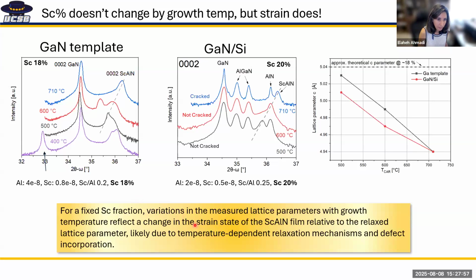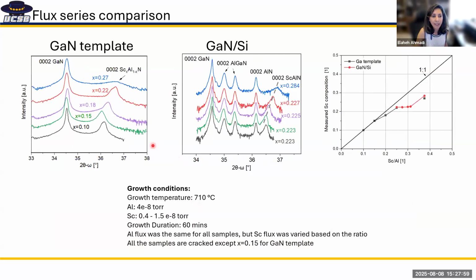incorporation. Another thing we have looked at is the fluxes basically, and what we have seen is that as we increase the scandium to aluminum ratio for smaller compositions, it changes linearly, but as we go to higher scandium, as we are trying to incorporate more scandium and we increase the scandium to aluminum ratio, we see that the scandium incorporation doesn't go up linearly. It goes up, but it's not linear.